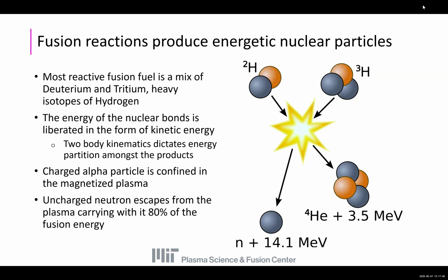So fusion reactions produce energetic nuclear particles. Deuterium and tritium are isotopes of hydrogen with extra neutrons, and it's the most reactive mix of fusion fuel we have. When deuterium and tritium react together, it emits an alpha particle and a neutron. The energy that's stored in the nuclear bonds within the deuterium and tritium is released in the form of kinetic energy in these products. And since it's a two-body kinematic reaction, the amount of energy that goes to the neutron and the alpha particle is a discrete quantity. Every time you get 14 MeV of energy to the neutron and 3.5 MeV of energy to the alpha particle.